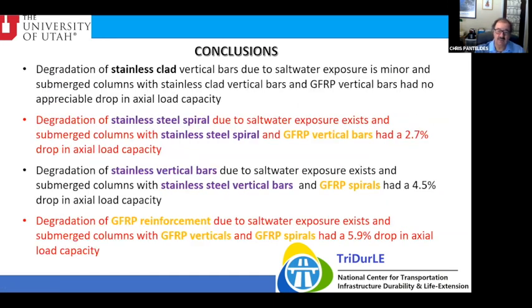Degradation of the stainless clad vertical bars due to this saltwater exposure was minor, and the submerged columns with stainless clad vertical bars and fiberglass vertical bars had no appreciable drop in axial load capacity. Degradation of the stainless steel spiral due to this water exposure exists, and the submerged columns with stainless steel spiral and fiberglass vertical bars had about a 3% drop in axial load capacity. The degradation of the stainless vertical bars due to the saltwater exposure exists, and the submerged columns with stainless steel vertical bars and fiberglass spirals had about a 4.5% drop in axial load capacity. So we also saw that GFRP reinforcement can degrade in saltwater exposure, and the all fiberglass columns, both verticals and spiral, had about a 6% drop in axial load capacity.